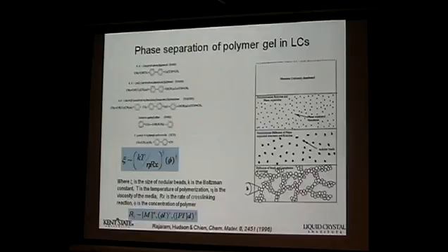So if you are shining a huge light, turn on too many lamps, they're going to cause this phase separation to go very quick, and that's the problem. If the phase separation goes very quick, the nodules that you see, the defects of those, are getting smaller and denser, and creating more defects. So you have to control that. Certainly the viscosity of the host also determines the diffusion rate.